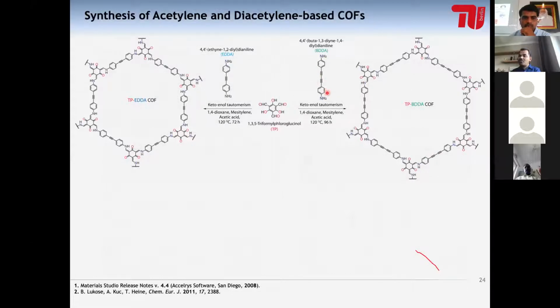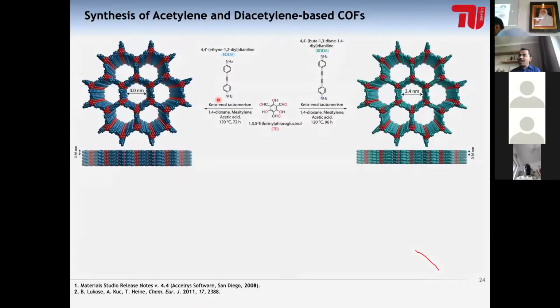For doing that, we installed this diacetylene moiety in a diamine molecule, as I showed earlier. We also installed the acetylene moieties in another diamine molecule. We started reacting these materials with 1,3,5-triformylphloroglucinol, which is a trialdehyde. When we reacted these materials with each other, we got materials which should ideally have a structure like this. This is the structure we generally expect in these cases, but it should be crystalline. By using 1,4-dioxane and acetic acid as a catalyst at 120 degrees Celsius for 72 hours, we could synthesize materials which should ideally be structured something like this. So now, if we get a material out of these two components, this should have the exact structure that I showed here.